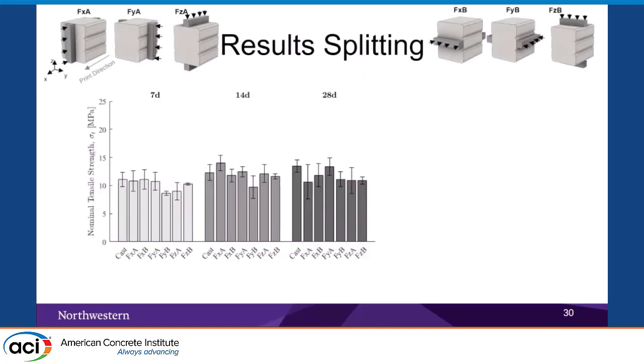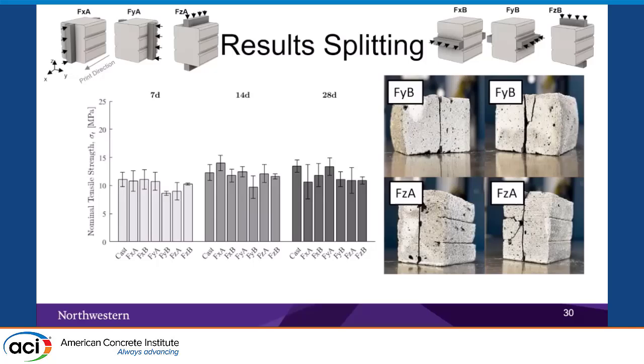For the splitting test, here we can see the qualitative geometric effects. The crack is in the middle, but also because of the printed layer features, we don't have just one crack, we have multiple cracks. Right now we are working on a numerical simulation of those observations to understand more about what's going on when including the printing features.